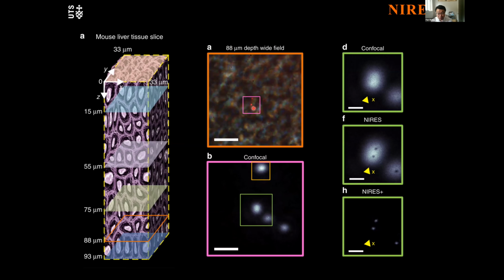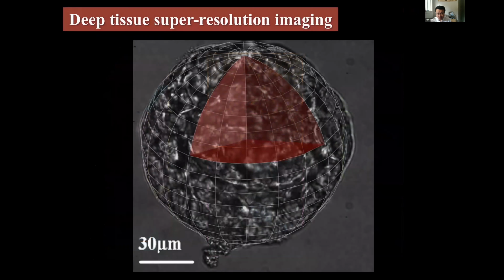So if we put some particle inside this deep tissue and use near infrared confocal, we can see the particle, and with the super resolution and with deconvolution, we can still resolve this particle. Which means that we can achieve super resolution of 50 nanometers through this 100 micrometer tissue. But it's still not enough. The reason why is, apart from just looking at something through the tissue, we're also interested in researching this kind of sample. So this sample is called organoid.